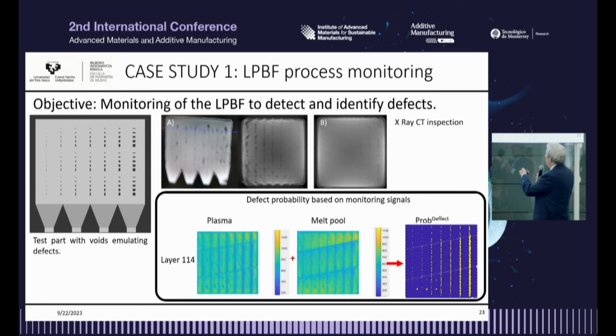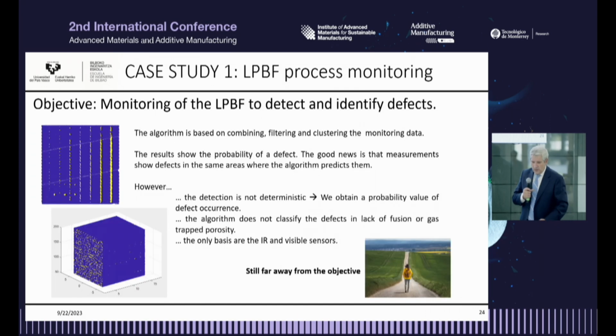So, and those are the monitoring data, and we have implemented machine learning algorithms in order to obtain a map of probability of defects. So the blue areas are good areas, and the yellow areas are high probability of defect. The algorithm is based on combining, filtering, clustering all the data, and the results are very good. The probability of defect is detected, and the good news is that the measurements show that the defect areas are where they are located. So in that case, it seems that we are on the good way.